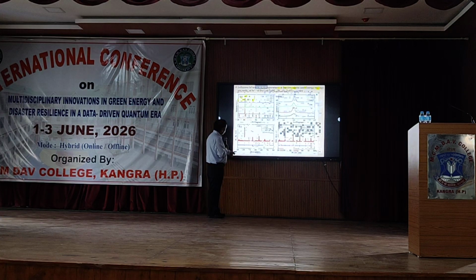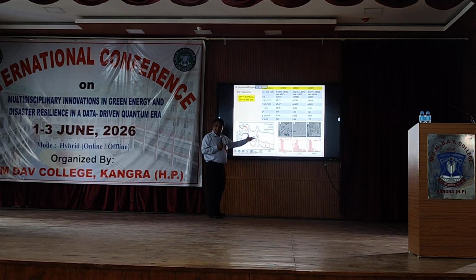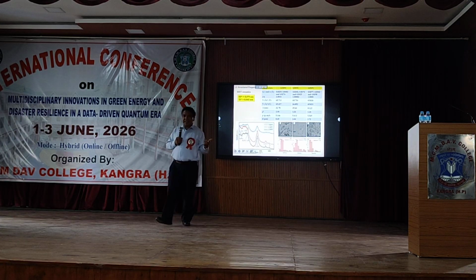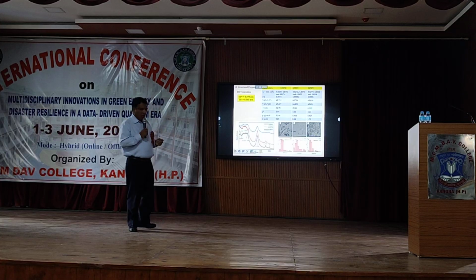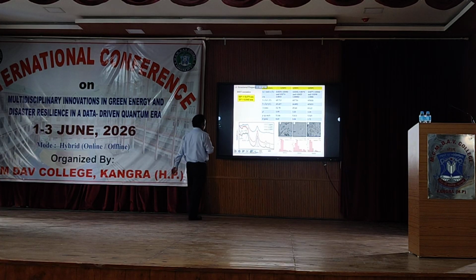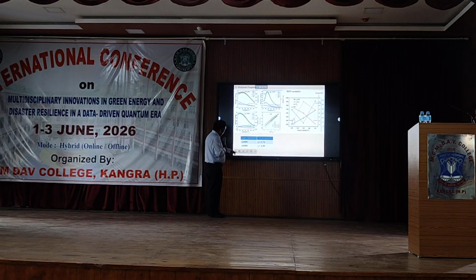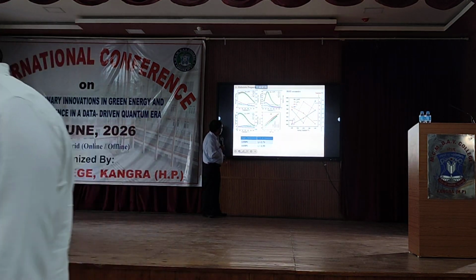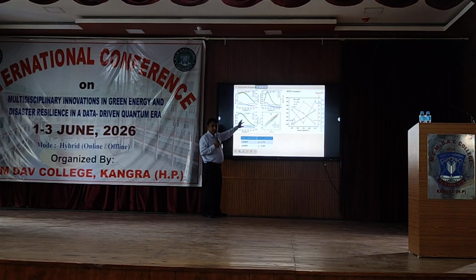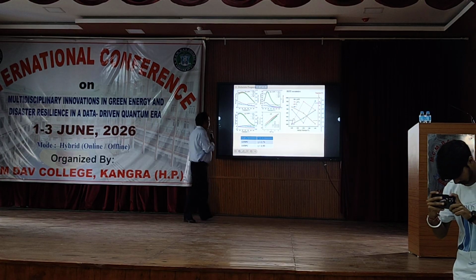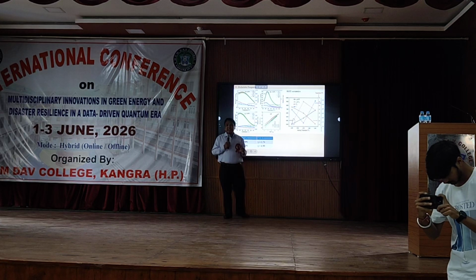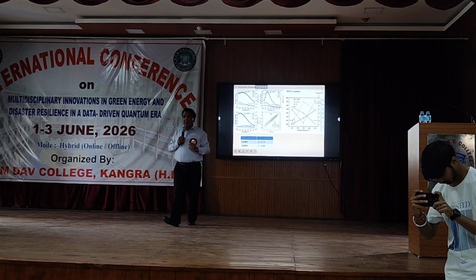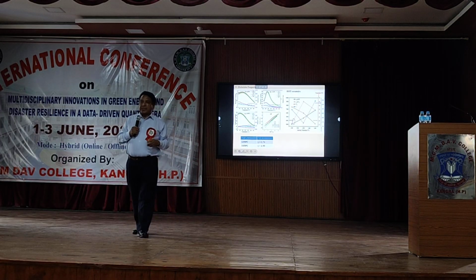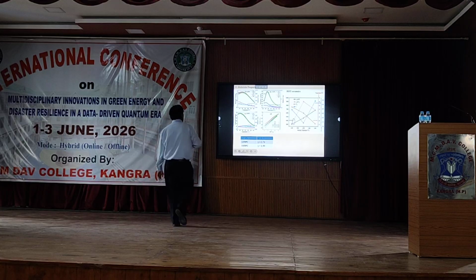So one can see here a lot of structure data, microstructure, Raman. We have to confirm whether the materials have achieved the required structure or not. We confirm by this kind of microstructure, but I want to show, because of constraint of time, the final result, that is the dielectric property, where one can see these two have diffuse phase transition, and this one is the ideal kind of thing. Diffuse phase transition is the signature of a relaxor ferroelectric, where it has polar nano regions so as to enhance the electrocaloric effect and energy storage performance.